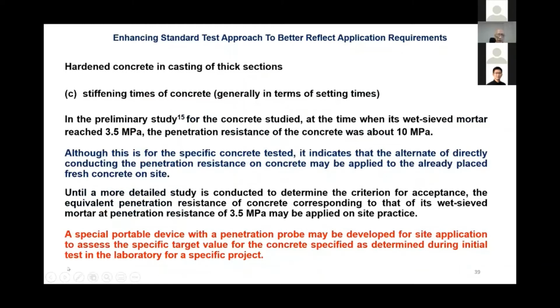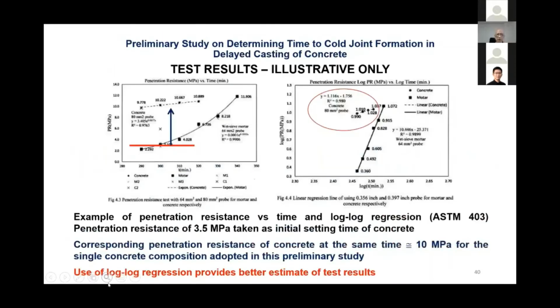So that means now we have a way eventually to design a probe that can test our concrete by resting the equipment on top in a raft foundation, on top of the reinforcement bar on the top gauge, and push it down to whatever layer down below, 3-4 meters below, and test what is the penetration resistance of the concrete before we add the next layer after a few hours of delay and avoid a cold joint. So that gives us something very meaningful.